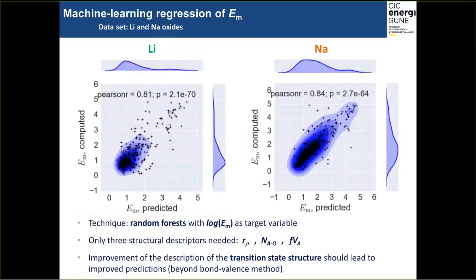So improvement of the description of the transition state should lead to improved predictions, but this will of course require more computationally intensive techniques, such as density functional theory, for example. In this regard, this technique can become really powerful if implemented at early stages of more complete automated workflows, like the ones described before by Thijs in his presentation, where actual diffusion path searches and transition state optimization can be performed in DFT and NEB algorithms, for example.